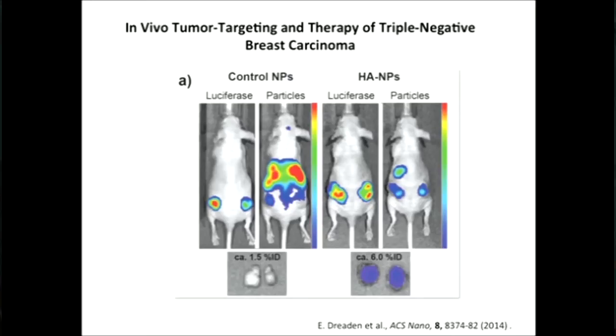And you can see the effect of this when you look at our other layer-by-layer nanoparticles, which don't have hyaluronic acid and don't exhibit some of these properties I described. You do a tail vein injection. On the left, we have luciferized tumors, so they glow. And these are the tumors on the left here. And when you inject, and then you change your wavelength so that you're observing the particles instead, you can see the overlap is not very high. A little in the tumor and a whole bunch in the liver.